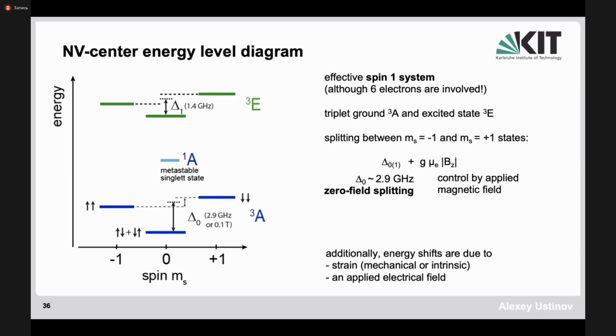Actually, I'm not really a specialist there, but just to give you an idea, you have here the singlet and triplet states of this spin 1 system. The triplet state with the lowest energy is the superposition state, which is shown here. This is the state called the lowest energy state 3A. This is the ground state which has no spin because it's a superposition state, but the two excited states of the same group are separated by a small energy, a few microelectron volts. And these are the spin up and spin down states, which are shown here by two arrows up and two arrows down.